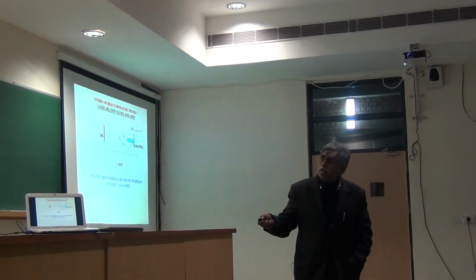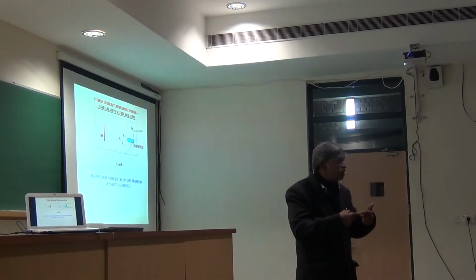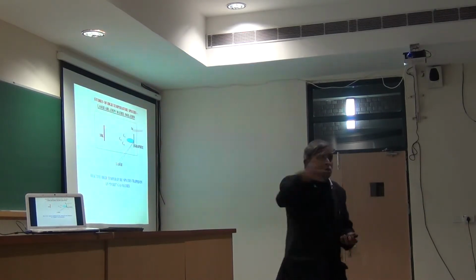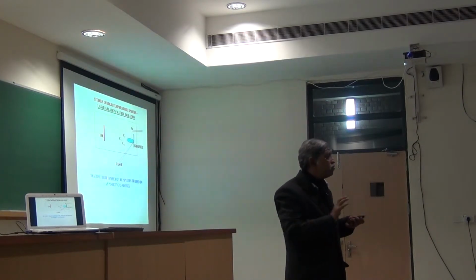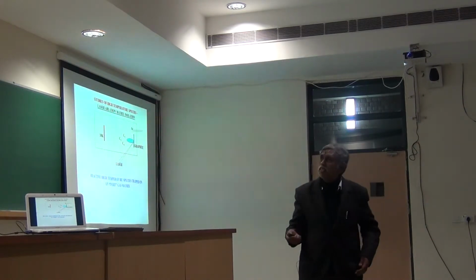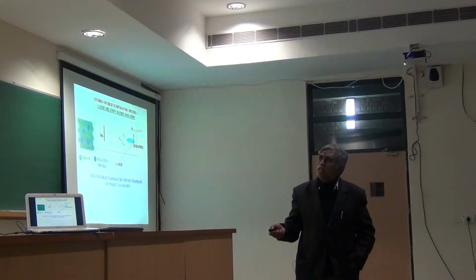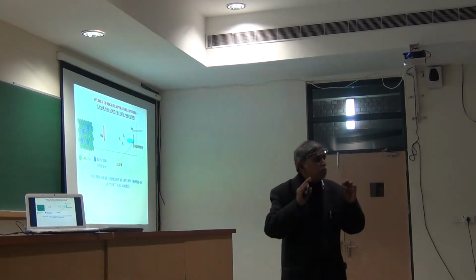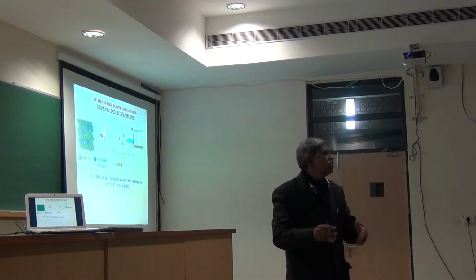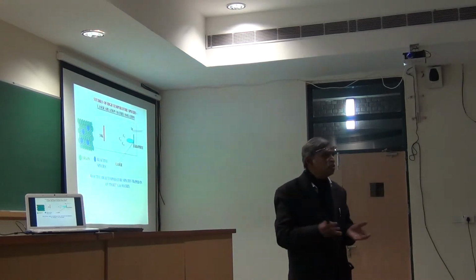And once they deposit here, they could react with each other. Oh, but then what I have done is brought argon in between and simply isolated them from each other. So I now have a situation in which here is a C2, maybe a C3 here, and a C5 here, and a C7 here, and so on. And I have argon everywhere. So the C2, C3, C5, C7, all of them absolutely itching to react. There's nobody to react with. And that's the whole idea.